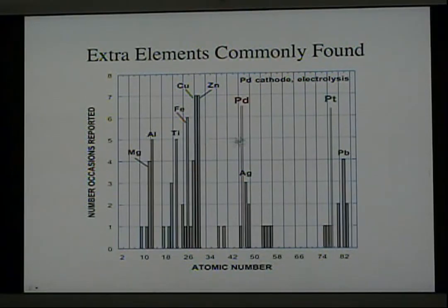It would appear that the palladium, after taking up a proton or a deuteron, splits into two fragments, which are these elements. If this split does not happen, then these elements might be formed as more deuterons or protons are taken up by the palladium. The problem is to explain something so heavy as lead.